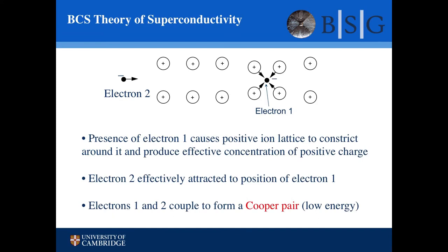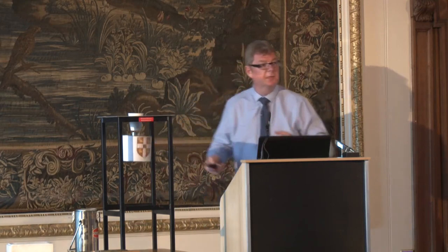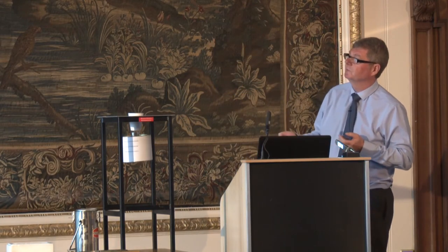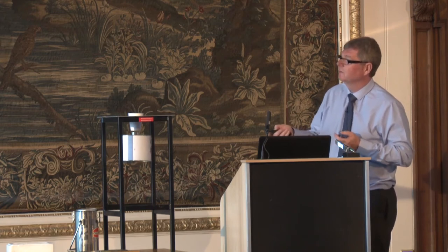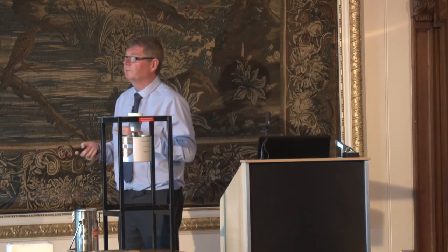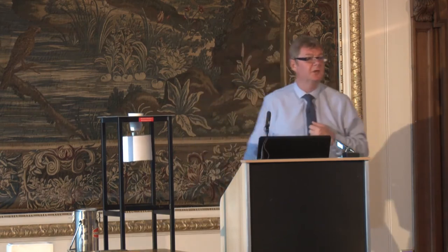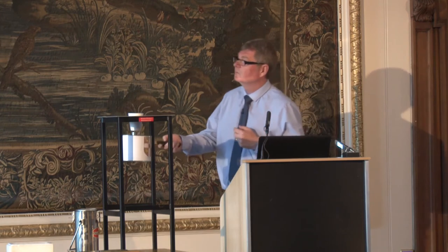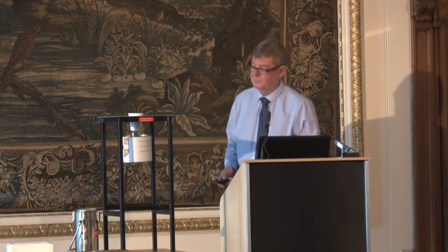And essentially what's happening is that if you take a very specialized lattice of charged particles, positively charged, and you put an electron in the vicinity, you get a contraction of the positively charged lattice around the first electron. And then a second electron, rather than seeing the first electron, sees the buildup of charge around it and is therefore attracted to it. So via some complex interaction with this very specialized lattice, electron two is attracted to electron one. And it's this coupling that reduces the energy and therefore will happen if it's possible. This contraction of the lattice is called a phonon. And obviously, if you go to high temperatures, these lattice ions are vibrating around all over the place, and any small contraction can't be seen, which is why superconductivity is traditionally a low temperature phenomenon.